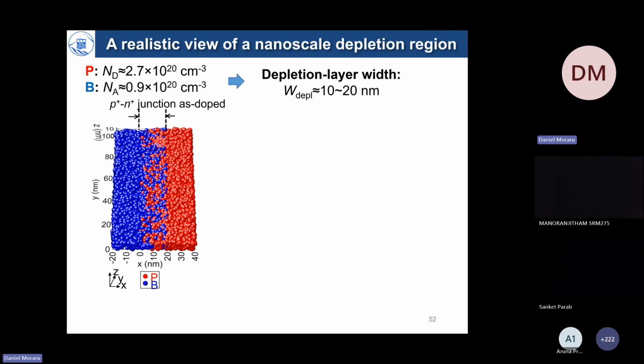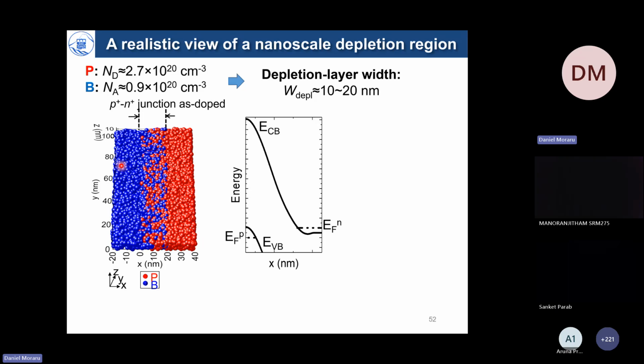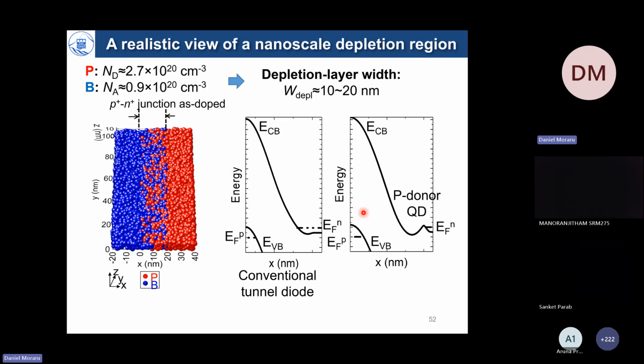Dopants are randomly distributed, boron on the left, phosphorus on the right, and both of them mixed at the junction point. So if the dimensions of the device are very small, then this mixture creates random structures. And if you take a scan through any of these points, you may observe a regular p-n diode band diagram in some points, like a conventional tunnel diode, but in other points, you could observe quantum dots embedded into this band diagram and modulating it very significantly. So this kind of view arises from the random distribution of dopants in these low-dimensional diodes.